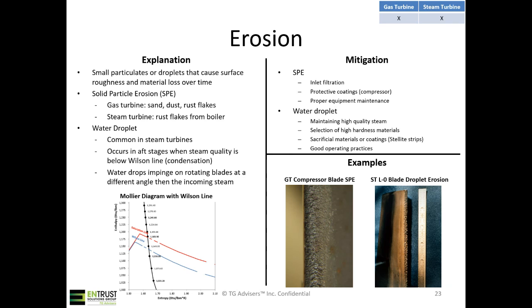A lot of times you'll see those coatings on compressor blades, and then proper equipment maintenance. Water droplet erosion, best way to mitigate that is maintaining high quality steam, selecting high hardness materials or sacrificial materials. A lot of times there's stellite strips that are used on the leading edge of L0 blades, and there's also good operating practices and to make sure that you don't have too much water in your turbine, and that's obviously